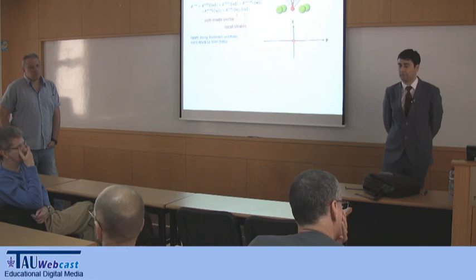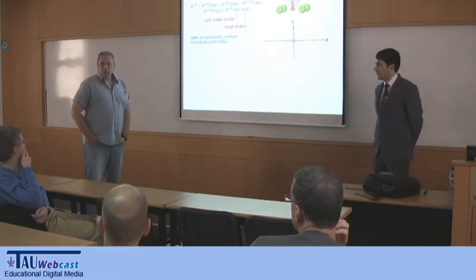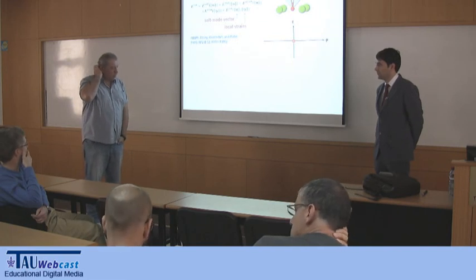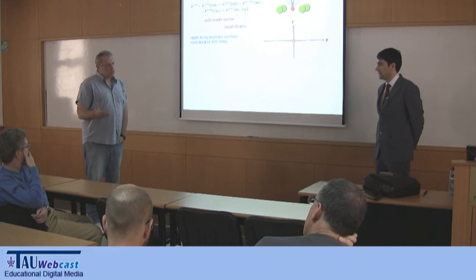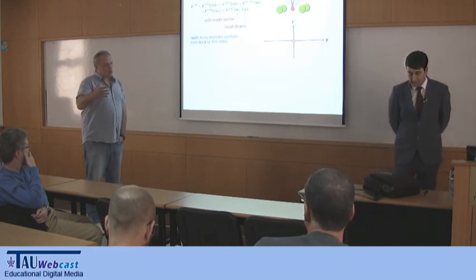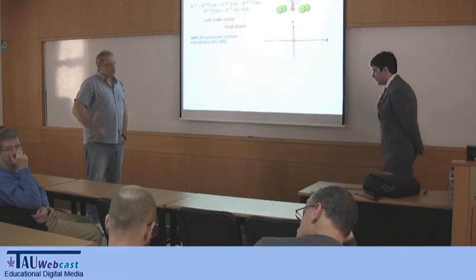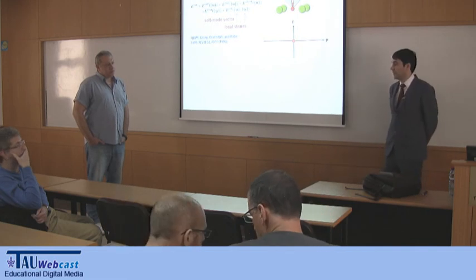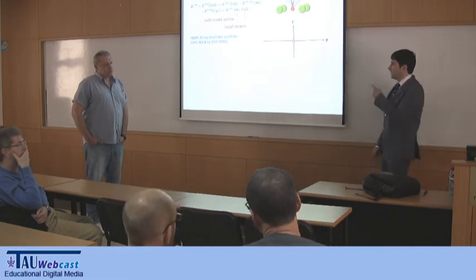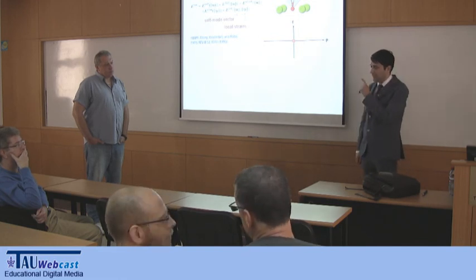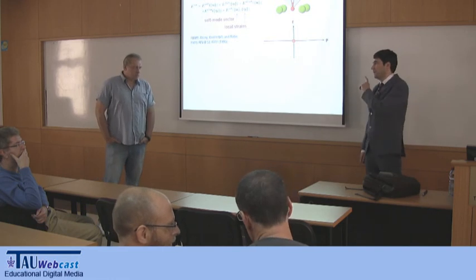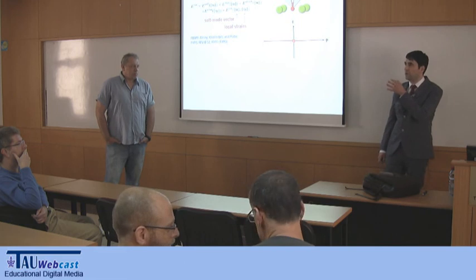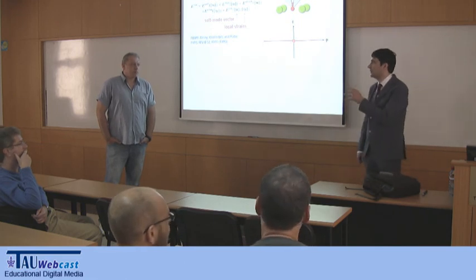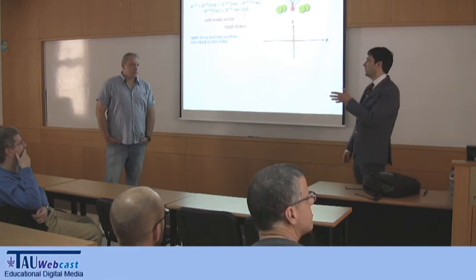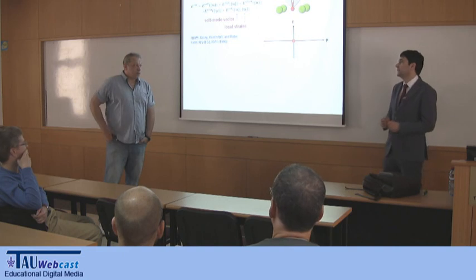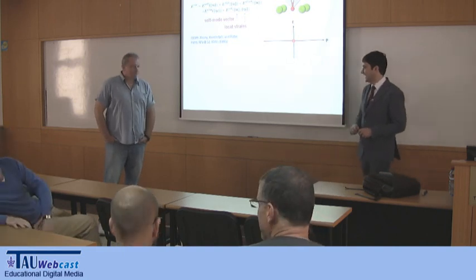There, again, Cesar. I guess that your work on the domain boundaries will crucially depend on working with experimentalists, in particular TEM or high resolution people, to characterize the domains and their morphology. Yes. The reason why DFT studies are relevant is precisely because even with TEM, the atomic displacements are very, very small in perovskites. In bismuth ferrite, maybe they are of the order of 0.05 angstrom, something like this. The resolution of TEM is getting there, but not there yet. So basically, with TEM, unless you have the Cs-corrected TEMs, the last and fantastic development, I guess.